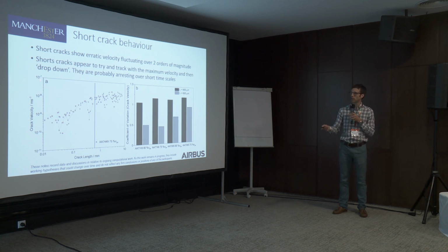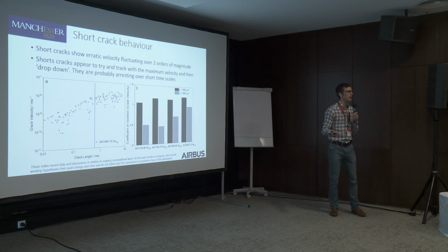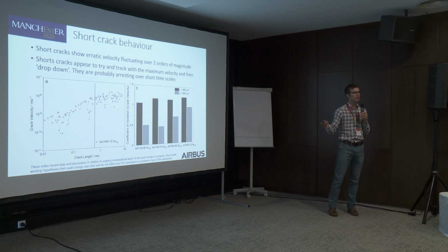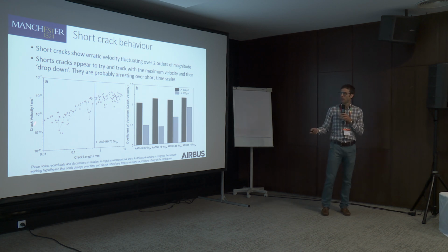So now plotting the crack velocity as a function of crack length, we see what I've plotted here as a coefficient of variation, which is basically how erratic that crack growth behavior is in the short crack regime and in the long crack regime. And we see we get much more erratic behavior of the cracks. And actually our time interval for measurement is about 2 hours to take each one of those tiled arrays of images. And I think that these cracks are actually arresting intermittently, and that coincides with the observations of